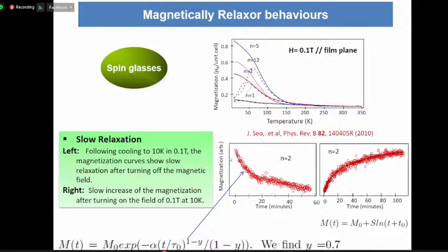See this case, we turn on the magnetic field and turn it off. Then we measure the magnetization as a function of time. Even around 1 hour later, the magnetization is slowly decreasing. Also, when we turn on the magnetic field, the magnetization goes up until 2 hours. So the magnetization is moving very slowly. This behavior is a very typical characteristic of spin glasses.